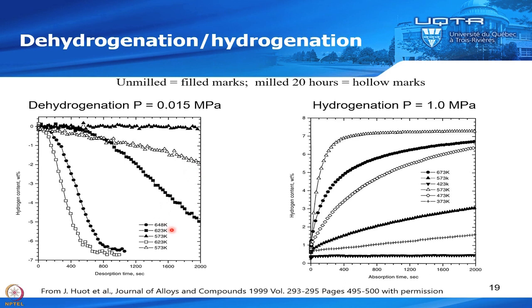And if we look at 623 K, so 350 degrees C, this is the desorption of the unmilled one, and the milled one is here. It's much, much faster. It's totally desorbed in 800 seconds, about 12 minutes, while here after half an hour it's still not fully desorbed. And you see even the unmilled one at 648 is still slower than the milled one at 623. So ball milling, just getting a nanocrystalline structure, drastically improves the desorption kinetics and also the hydrogenation kinetics.